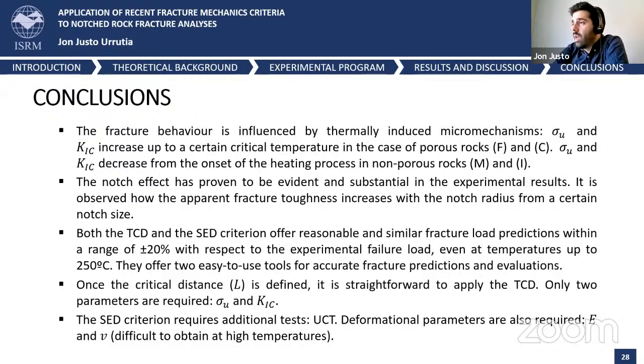It's important to highlight also that both the theory of critical distances and the strain energy density criterion offer reasonable and similar fracture load predictions within a range of plus minus 20%. This strip is quite common in fracture mechanics to consider the accuracy of any criterion. So they were valid even at temperatures up to 250 Celsius degrees, as long as linear behavior was observed. So they both offer two easy to use tools for accurate predictions and evaluations. In fact, the first one, the theory of critical distances, once the critical distance is defined, it is straightforward to apply the theory.